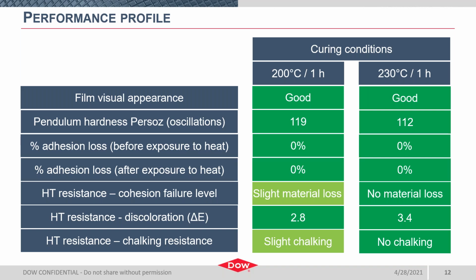And delta E, or color change, was calculated between a cured film and then a film that had been exposed to heat. We also looked at humidity and water resistance, but I'm going to share that data on a later slide. The post-heat data for this slide and all other data I'm going to share indicates it was exposed to 500 C on a hot plate, and this was really to simulate what the coating's going to see in a real-world application.